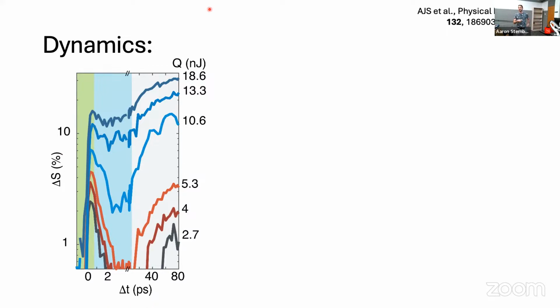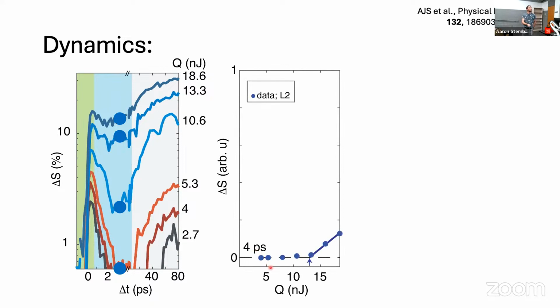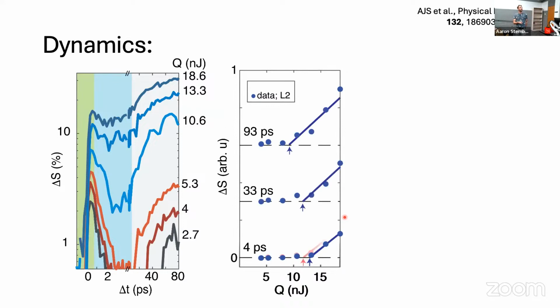So this data, all collected again at a single location in our film, is sort of a summary of how the system evolves as a function of time and fluence. At a given time delay, say 4 picoseconds, you could take this data and just plot the change in near field amplitude as a function of fluence. And again, you see a fluence threshold. If you look at a later time delay, then you actually see that there's a reduction in the fluence threshold as a function of time delay. And at a neighboring location, we repeated all of these measurements and saw that there was, again, an inhomogeneous time-dependent fluence threshold.